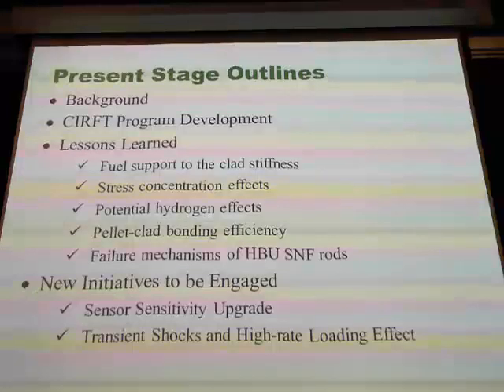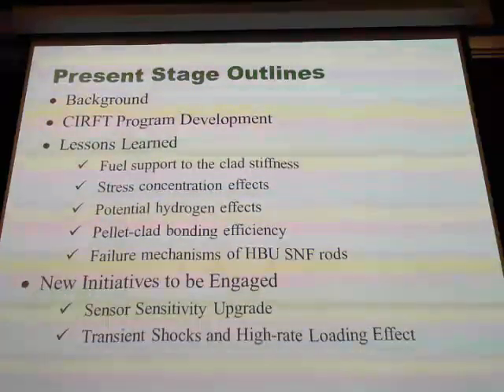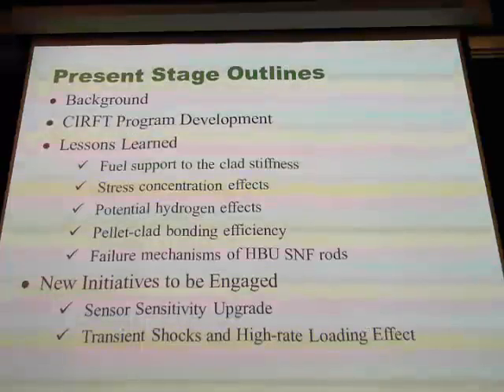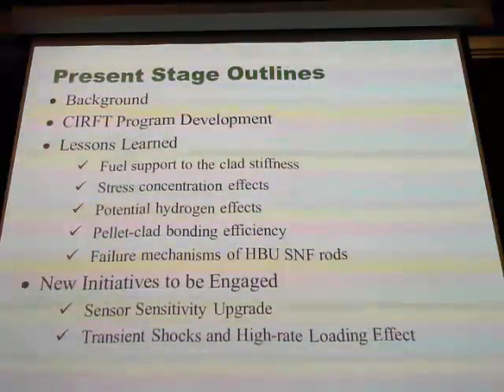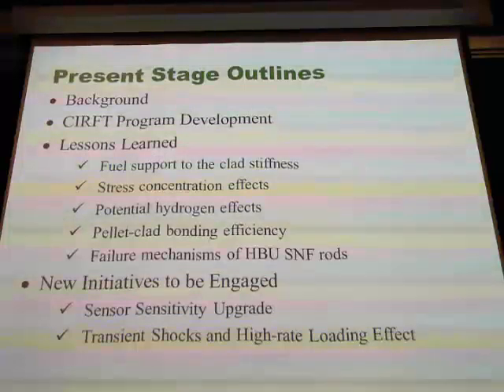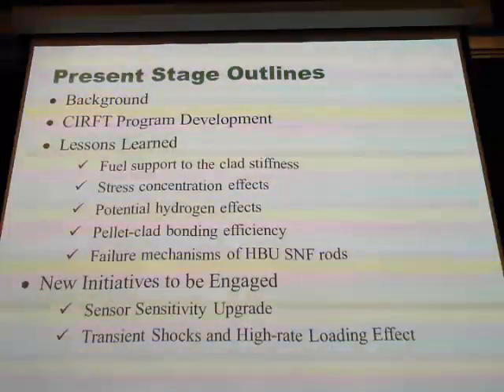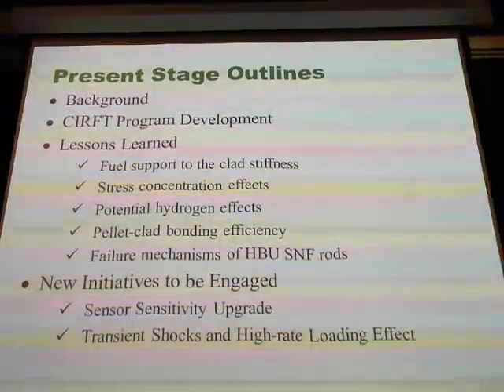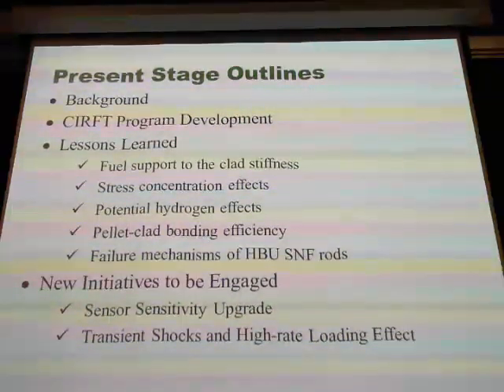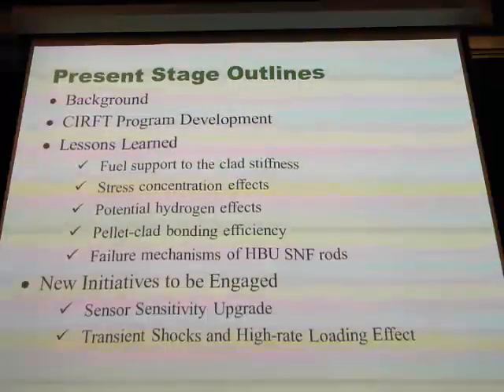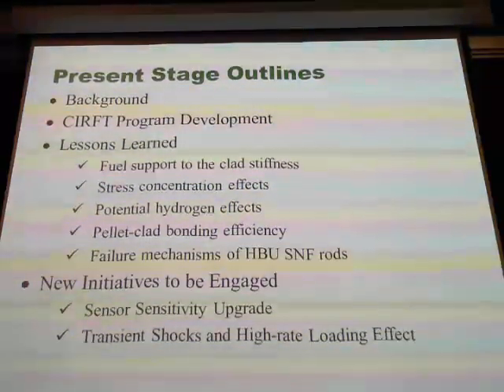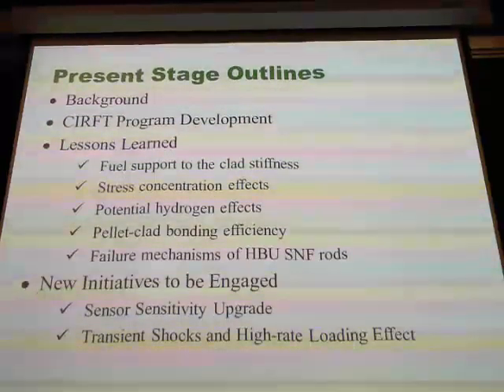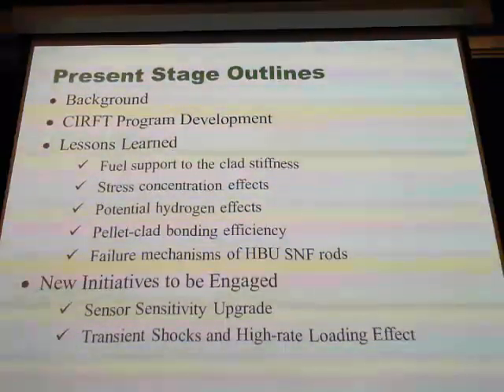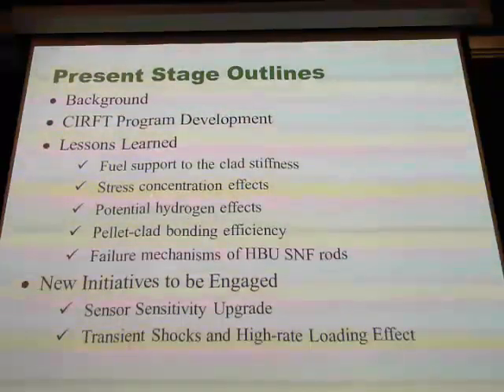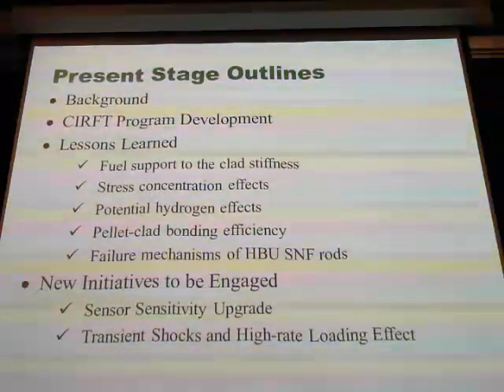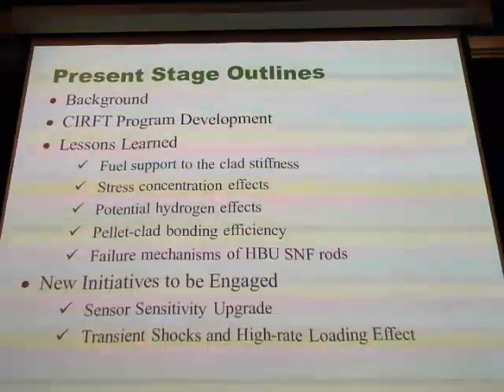In a high burnup fuel, eventually the fuel, during the radiation creep, will also contact your fuel cladding. And BWR and PWR are different. Pressurized water reactor at 2500 PSI fluid seems to have more contact. But the question is whether this is truly cohesion bonding or mechanical residual stress bonding. And the failure mechanism, we see very clearly different fuel design, different pellet design, different radiation environment, all are different responses. Really warrant case by case study. It's really hard to generalize.